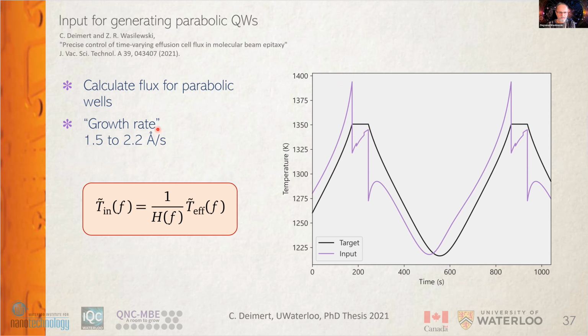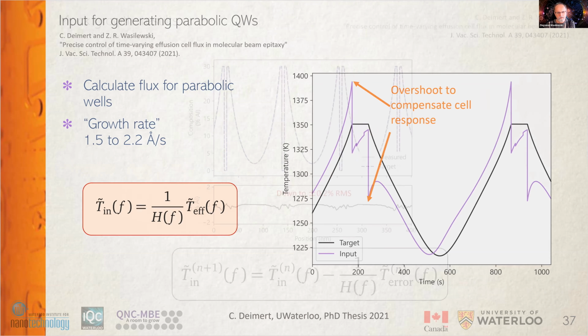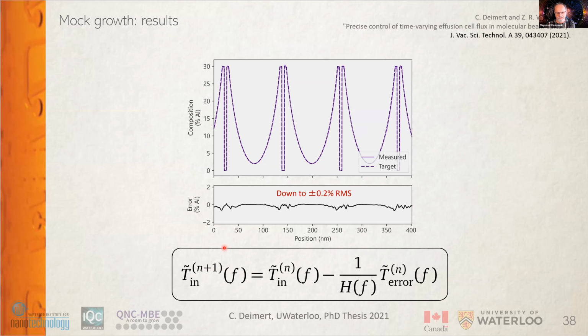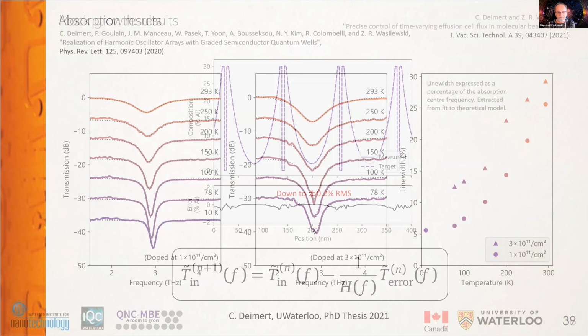So with the very respectable growth rate, it turns out that we were able to achieve extremely good reproducibility for those parabolic quantum wells, with errors of the aluminum composition better than 0.2%. And this was a real breakthrough in the field.